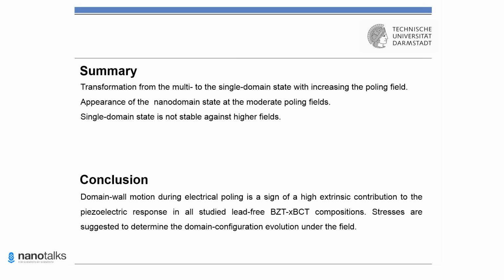So first of all, I would tell you what I think is very important for that kind of materials. Extremely interesting would be to perform electric field experiments at higher temperature, because the influence of temperature-induced phase transition during poling process on this material is not really studied and is not clear. In order to optimize its application, such studies are required, of course. I believe one possibility would be to use MEMS-based holders, for example, where you can apply voltage and at the same time increase temperature. So yeah, this would be interesting, I believe.